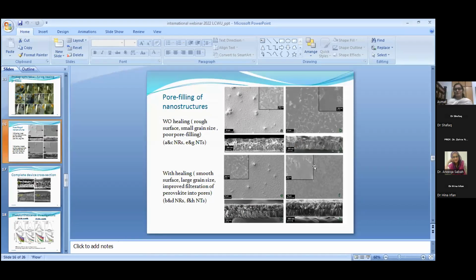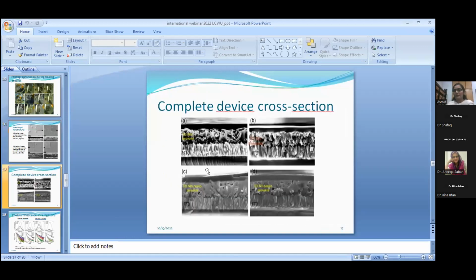So this is the complete device cross section with healing and without healing. The top panel is without healing, and the bottom panel is with healing. So we have this FTO, we have TiO2 nanotubes here and nanorods here with the infiltration of the perovskite, and here we have the metal contact. Here you can see the nanorods with healing, and there is a huge difference in the infiltration of the perovskite inside the pores of the nanostructures. And these are the nanotubes after healing.